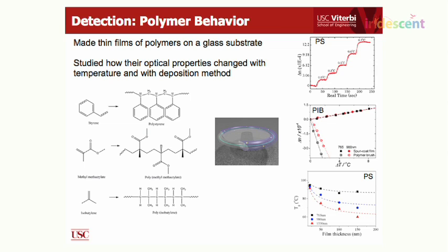And then depending on the film thickness and depending on what wavelength we measure, we get a different glass transition temperature. So the glass transition temperature is a parameter of a polymer material that describes when it goes from being solid to being viscous, so somewhat liquidy. So the glass transition temperature is one of those critical polymer material properties that you want to characterize. And there's clearly a film thickness dependence, which is known, but what this data shows is that there's also a dependence on how you're characterizing it.